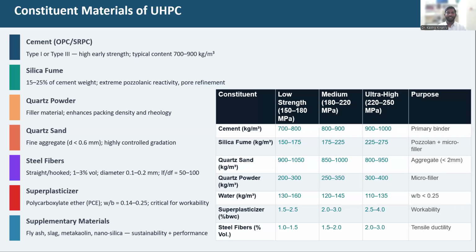It's not a cheaper material. So, considering that as a primary perspective, quartz powder can also be eliminated. Even despite eliminating the usage of quartz powder or even quartz sand, we can still attain 150, 160 megapascals of strength as well. There are some studies which proved that without utilizing quartz powder and quartz sand, we can still attain the required amount of target strength.